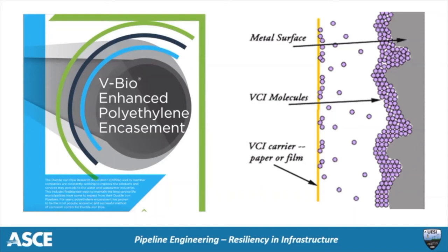The corrosion inhibitor will react to the development of a corrosion cell by sending molecules that attach themselves to the cathode and anode of an impending corrosion cell with molecules that build several layers deep. The bond is akin to a magnetic bond rather than an adhesive or chemical bond, so proper installation practice is required to take full advantage of this additive. In addition, the antimicrobial component will ward off the activities of the anaerobic bacteria that act as depolarizers that would otherwise allow the initial corrosion rate to continue unabated.